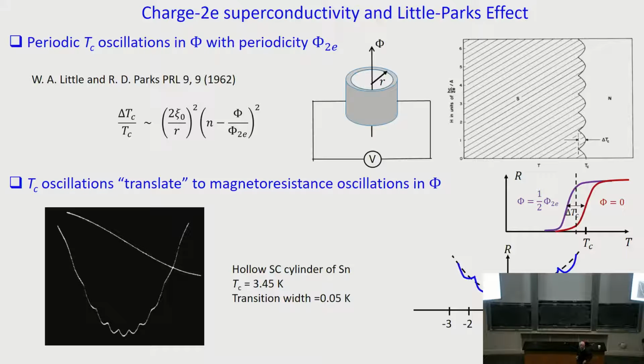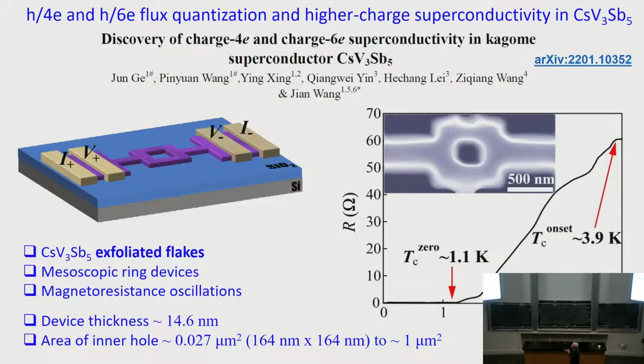Right? So obviously what should be done is try to do that on the Kagome lattice. Right? And this is what Wang tried. This, in the middle, is the ring structure. He wants to make this with flakes of this Kagome superconductor. This is about how thick it is. It's about 15 to 20 layers. And the whole central hole area can be as large as 1 micron squared.